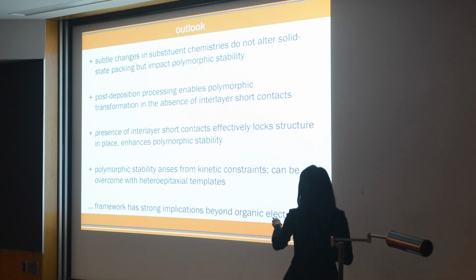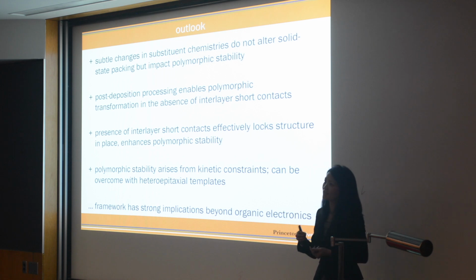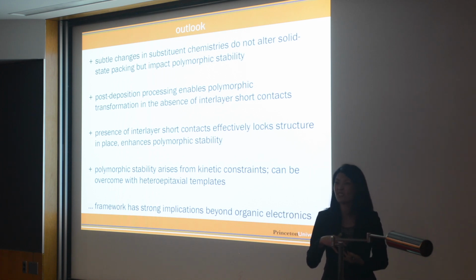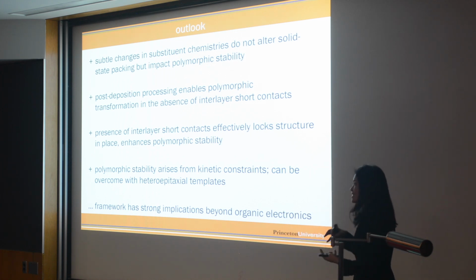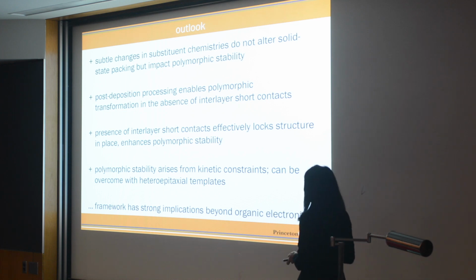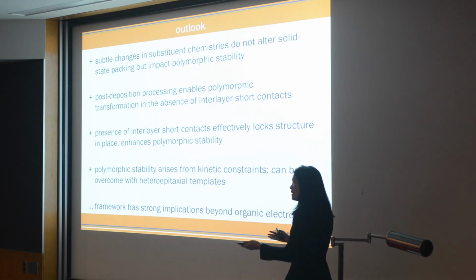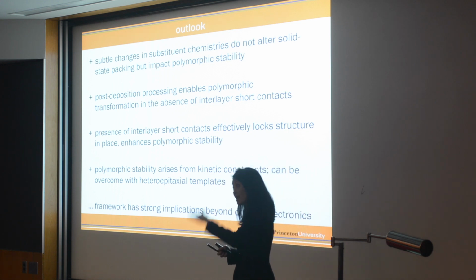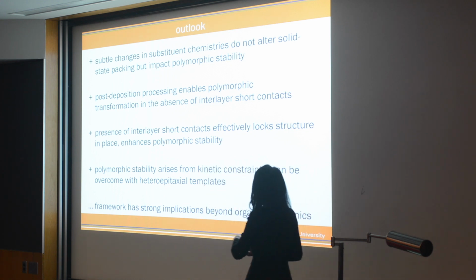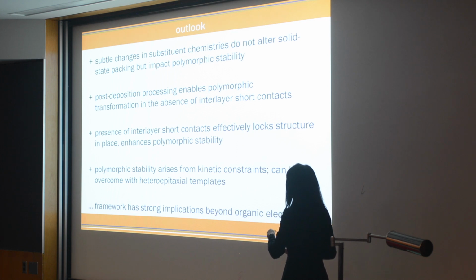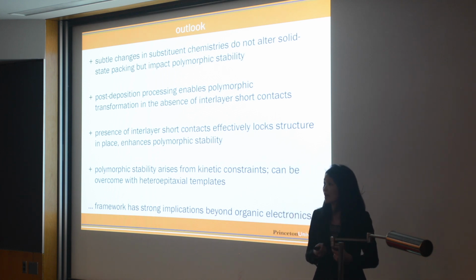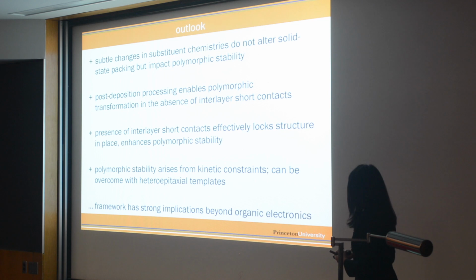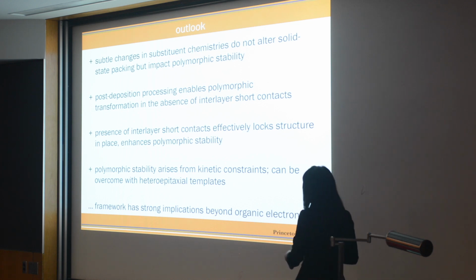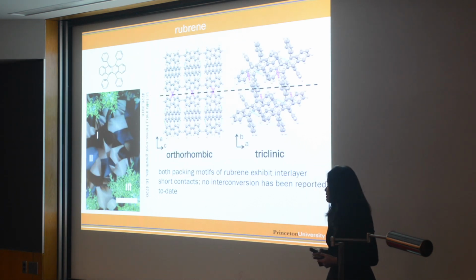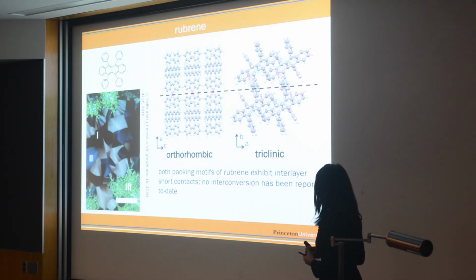But in the presence of these short contacts, we think these short contacts actually lock the structure in place, and so you're kind of stuck. But that stuckness is because of a nucleation barrier. And so if you have a template and you seed nucleation because you're bringing that barrier down, you can now access the other polymorphs. So it's a kinetic constraint that you can overcome with a heteroepitaxial template. And so what I'd like to show you is that this framework actually has strong implications beyond organic semiconductors. This is an organic semiconductor, but I'll come back to the non-organic semiconductor.